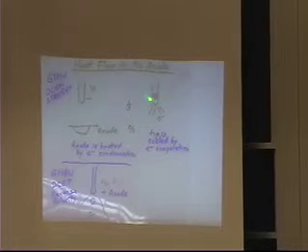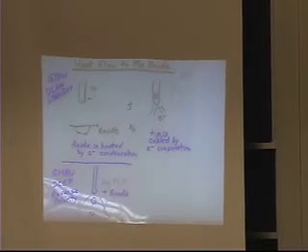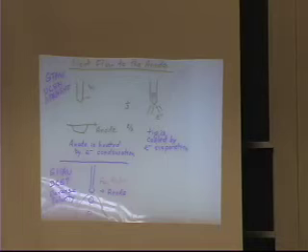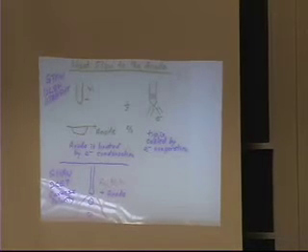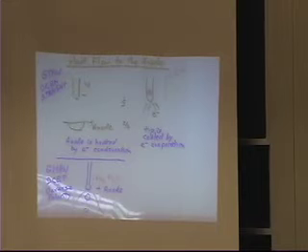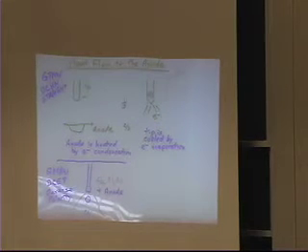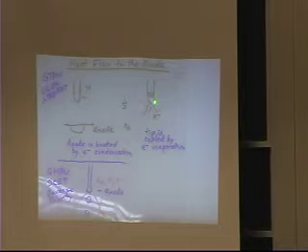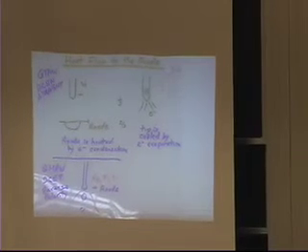It'll melt off back here and you'll get this little rectangle when you take images of it. You actually break off tips, or melt off tips. And I've talked to other people over the years, and they say, oh yeah, tungsten inclusions often are not little spherical balls from melting, or they don't know it's from melting, but they say, yeah, they have edges and corners. And that's because the tip actually is hottest right up here.